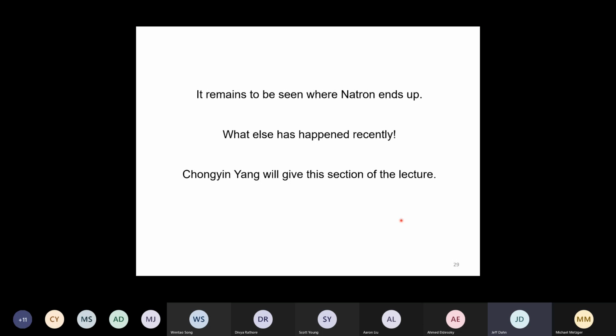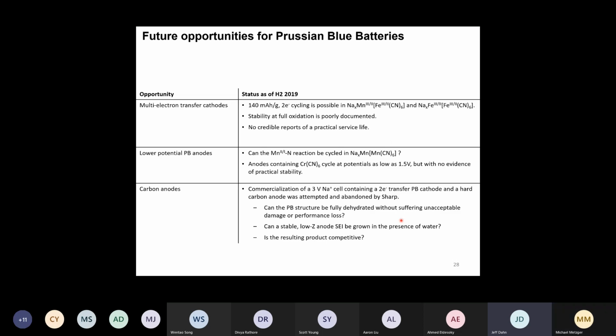I'd like to make a comment on the previous slide just for a brief minute. Yeah. So nowhere has anyone talked about volumetric capacity or volumetric energy density of this stuff. And I just want to share a rule of thumb that I have with everybody. If you think about lithium cobalt oxide, it has the lithium that goes in and out. It has the cobalt, which needs to be there to change its oxidation state. And then it has 2 other atoms, 2 oxygens that are there for the structural part. So the 2 oxygens really are junk atoms that create volume, but they're not really needed for the operation. If you think about LiFePO4, it has the lithium and the iron, and then it has 5 junk atoms. And the volumetric capacity of lithium iron phosphate is pretty terrible compared to lithium cobalt oxide.